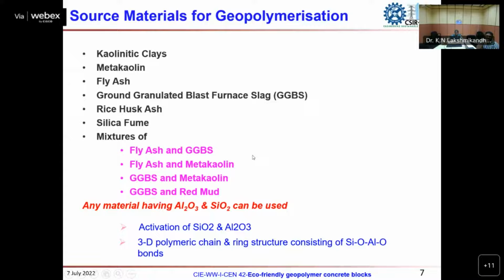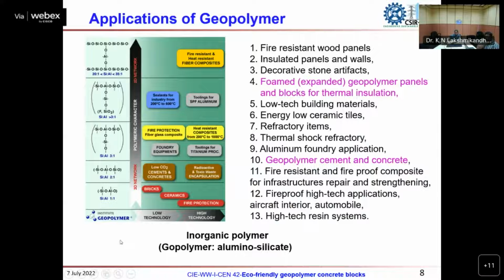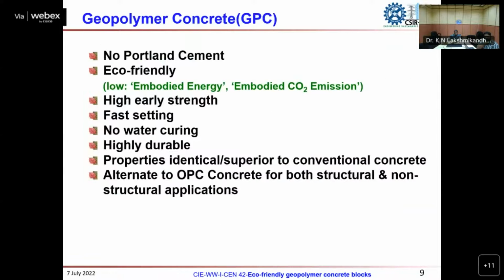There are a lot of materials which we can utilize for geopolymerization, for example fly ash, GGBS, metakaolin, red mud, rice husk ash, etc. We have used many source materials for geopolymer formulation, and depending upon the silica to alumina ratio in the source material, there are different technologies we can make. In short, wherever a conventional cement based system is used, we can utilize geopolymer as a binder, and there are a lot of advantages for geopolymer concrete.